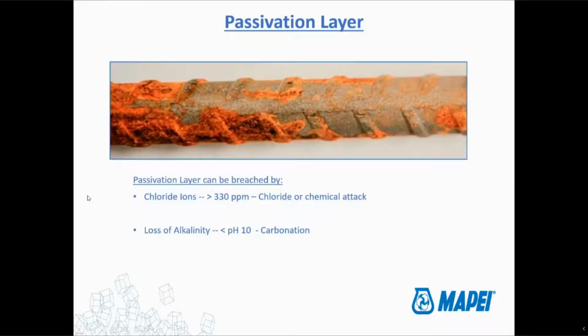The trouble is the passivation layer eventually is going to be breached. There's a couple of different ways that it can be breached. The first is via an influx of chloride ions. Different textbooks will have different numbers for what the exact number is, but generally around 300 to 350 parts per million of chloride concentration is sufficient to penetrate the passivation of reinforcing steel. So we're talking pennies difference here between 300 and 350 parts per million. It's not a lot. So you'll just see different numbers in different places. But the end result is really the same.